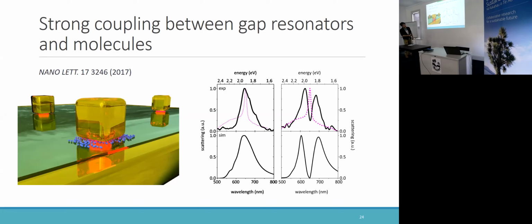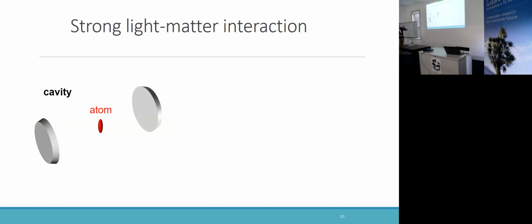And then we found out that when we place the dye molecules between the nanoparticle and the film, the single peak actually is split into two peaks here. We have two peaks when we put the dye molecules here. So that is a very clear indication of strong coupling between the photons inside the cavity and the material resonance. So here I pause to discuss the strong coupling.